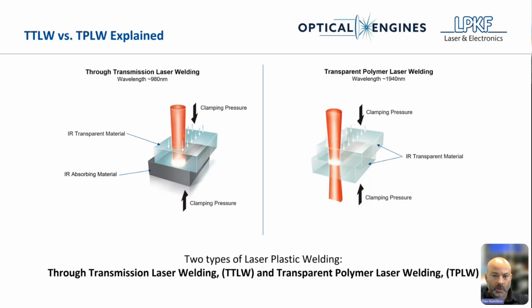And then for transparent polymer laser welding, we're using a wavelength in the range of 1,940 nanometers, or 2 micron. And both of the joining partners are IR transparent. They could be transparent to the eye, which is typically the case, or in certain specific cases, there can be dyes or color in these parts.